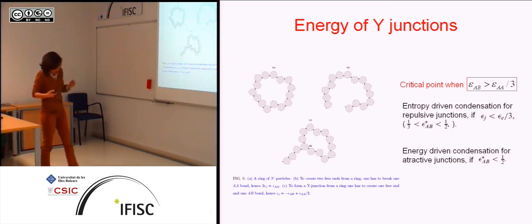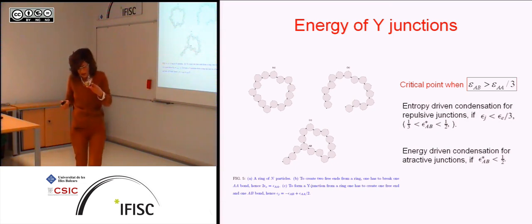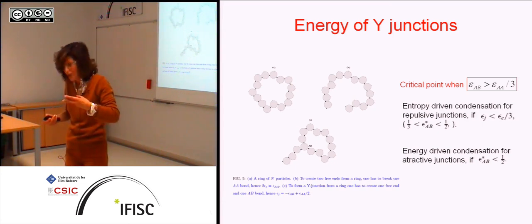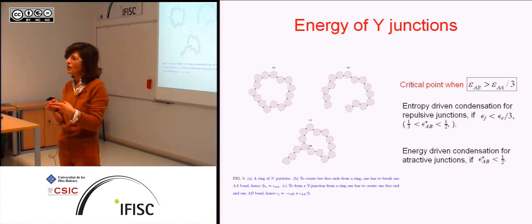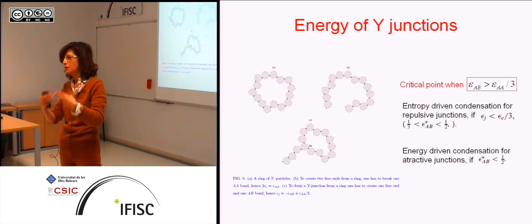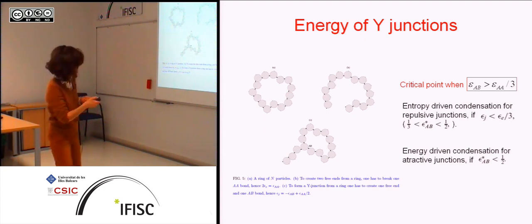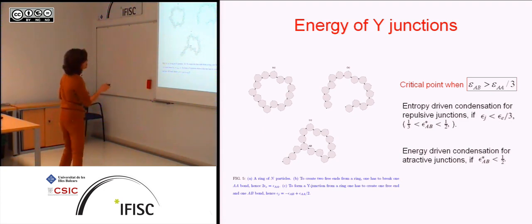So these junctions can condense in two ways. Either through entropic reasons, we can make this junction energy still repulsive, but they still condense because, for entropic reasons, the chains like to have junctions. And this is what Safran had predicted.